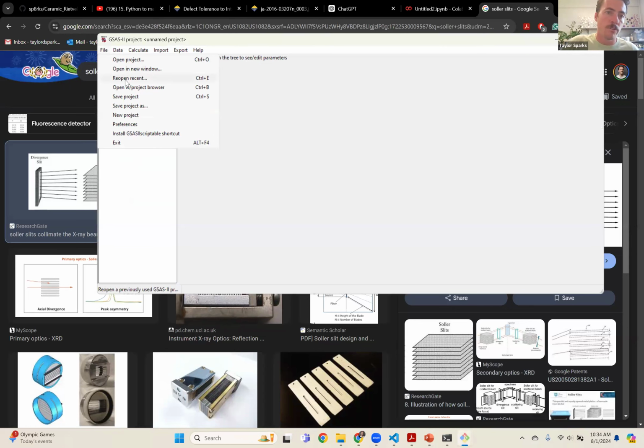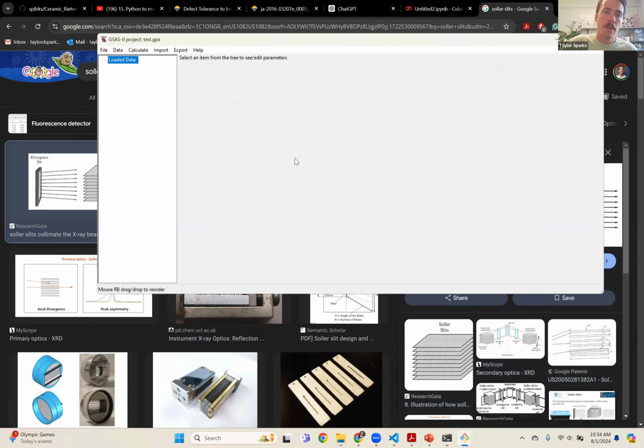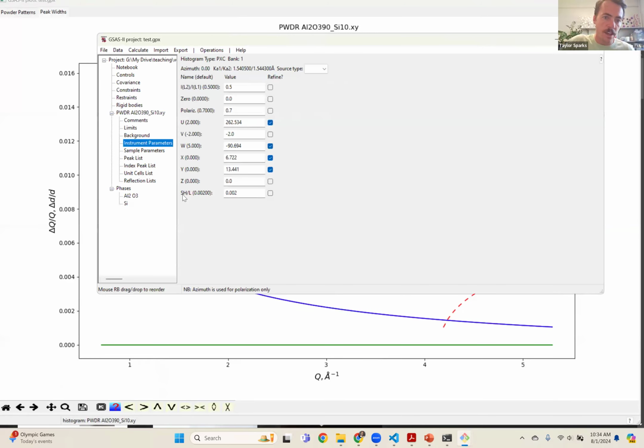like let's go to one of our files that we've been working on. Whatever this one is fine. And under your instrument parameters, there was that S/HL. So I'm going to go to instrument parameters. This one right here, this S/HL, that's your anharmonic, it's basically your asymmetry parameter. You're going to want to definitely turn that one on, but it's going to be harder to fit.